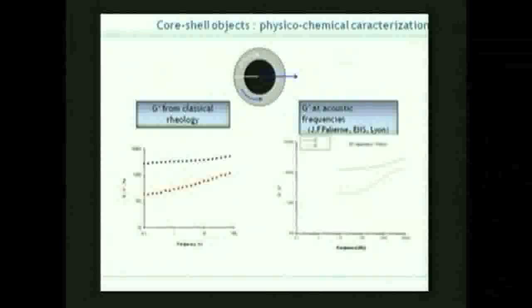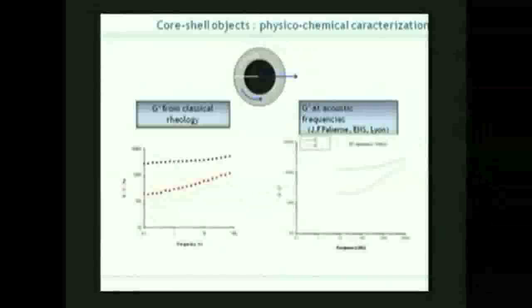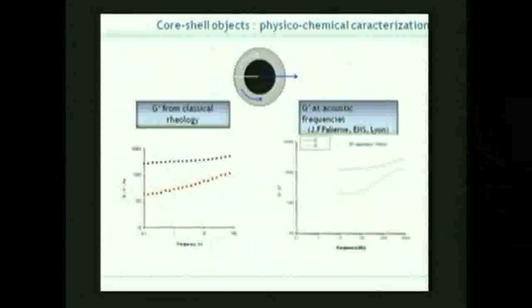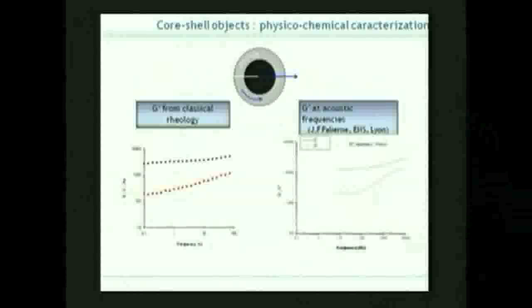So here is a curve of the evolution of these values as a function of the frequency, and we have been able to make some measurements in the high frequency range. Also in the high frequency range we see that we have a material that is more elastic than viscous, because the G prime is larger than G double prime, okay? So the gel in this shell is indeed an elastic material, even at the acoustic frequencies that we are going to look at now. Okay.